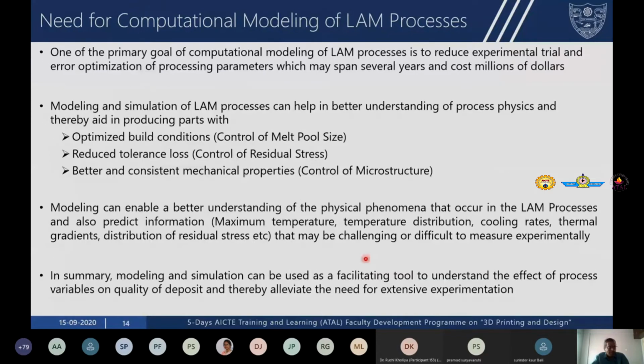So one of the primary goals of computational modeling is to change the way you traditionally optimize the processing parameters. Traditionally, processing parameters are optimized by the trial and error method. And this method used to span a few years and would cost a lot of money, several millions of dollars, to optimize the process parameters for a specific geometry from a specific material. Now, if you're able to model the processes, the advantage is that you'll be able to understand the process physics in a better manner that will enable you to produce parts with consistency in build conditions, lower residual stress, and consistent mechanical properties. And also, a number of times, modeling will enable you to understand the physical phenomena better, and it will also enable you to obtain information that is either difficult to measure experimentally or challenging, such as maximum temperature, distribution, residual stress, cooling rates, thermal gradients, and so on.